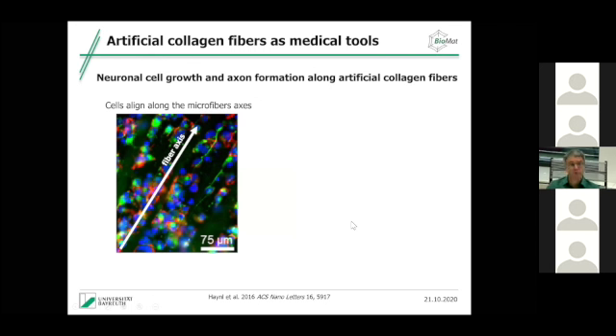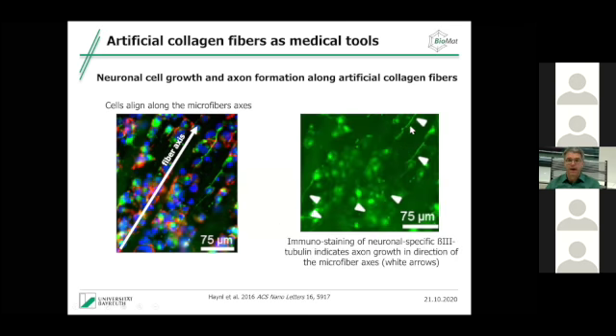But back to the neural regeneration, these collagen fibers that we produce with the microfluidics are also very well suited for neuronal cell growth. And again, the neurites and the axons grow along the fiber axis. And here you see them much better. So we can actually pre-align the neurons very nicely with these collagen fibers.